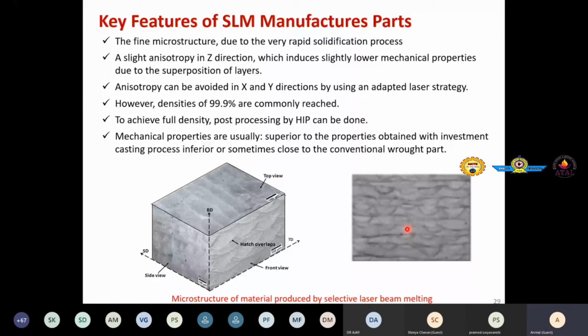And you see in each such a small melt pool, because of rapid solidification, we have obtained very fine microstructure, and that contributes to improvement of mechanical properties. But the problem is that along the build direction, we introduce some anisotropy. It means that along the build direction, because of layer-wise integration, the properties are weak. Okay. So the key features of SLM manufactured parts are a very fine microstructure due to rapid solidification, and anisotropy in the Z direction or build direction, which induces slightly lower mechanical properties due to superposition of layers.